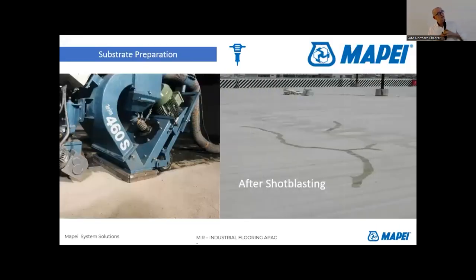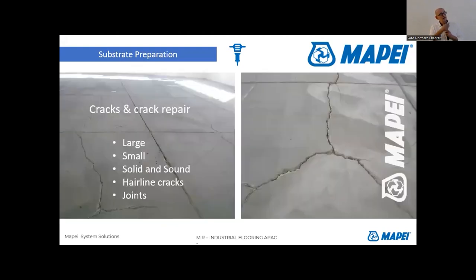And the key is if a shot blasting machine removes the first part of this layer, you see the cracks coming out slowly. Some are 0.3, there's some hairline cracks or larger cracks. We're having these kinds of movement cracks. They need to be prepared. This is very important. We need to knock around. Is it solid? Is it sound? Can I close this crack or do I need to remove everything?